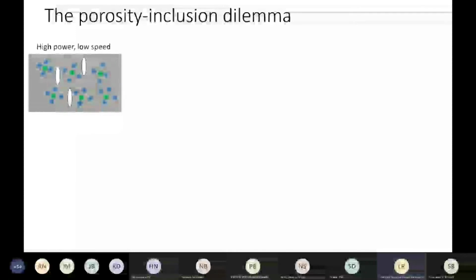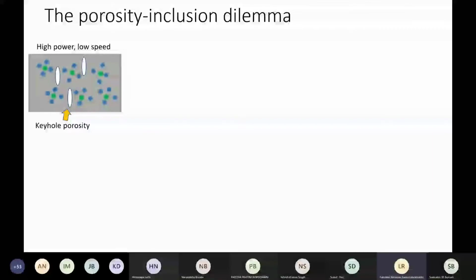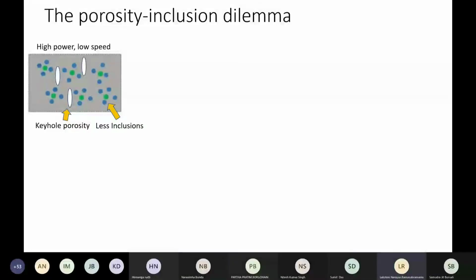Thus, we come to something known as the porosity inclusion dilemma, which is a fundamental problem in 3D printing. And if you can resolve this problem, you'll be very successful in building very high quality parts. So the first thing is when you use high power and low speed, you obviously know keyhole porosity will form because the laser will bore through the powder and it will heat quite a lot of material. Okay, because you have low speed, more material is exposed to it and you'll have a high aspect ratio melt pool. Apart from that, you will still have some inclusions, but they will be much fewer than what you would expect.